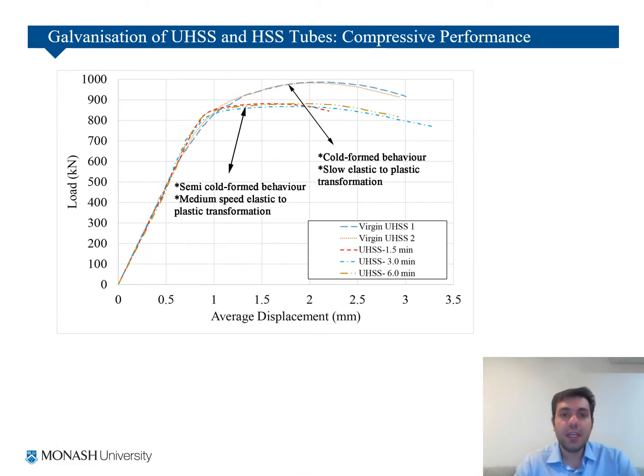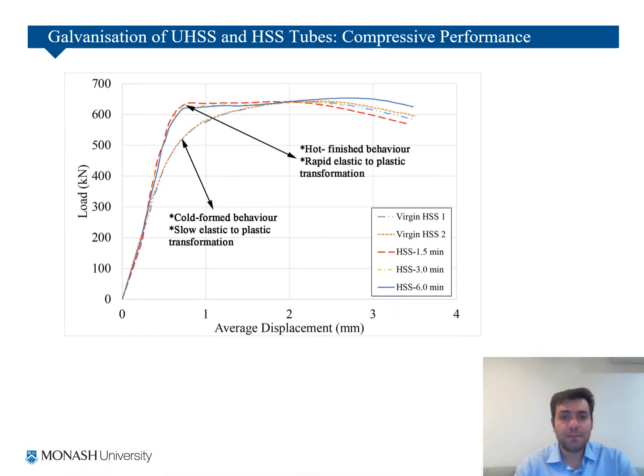Here you can see the compressive behavior of these tubes, and you can see that in compression, actually we didn't lose a lot of the capacity for ultra high strength steel tubes, but again the transition from elastic to plastic is faster. Here we didn't see much difference between different tubes galvanized for different durations. So in compression, the galvanizing time is not changing much of the material properties. For high strength steels, the transition is actually sharper, so the stress relieving and heat treatment, pseudo heat treatment in a way, of this galvanizing heat exposure worked.